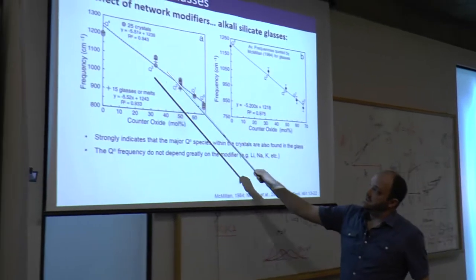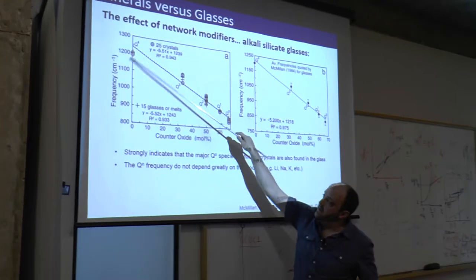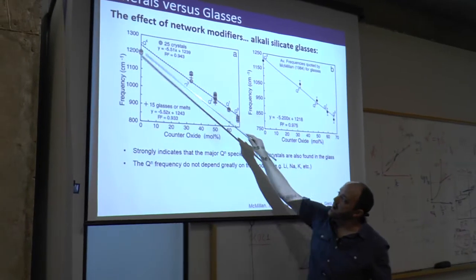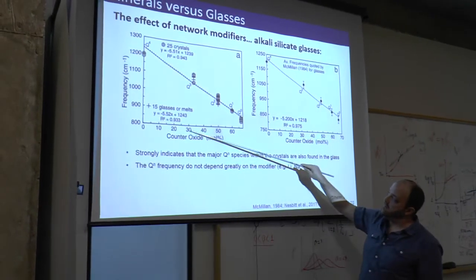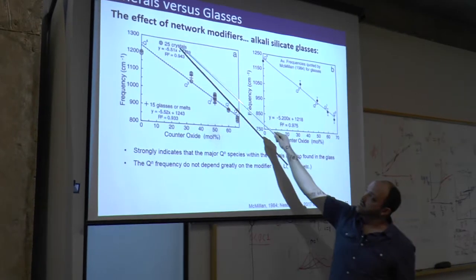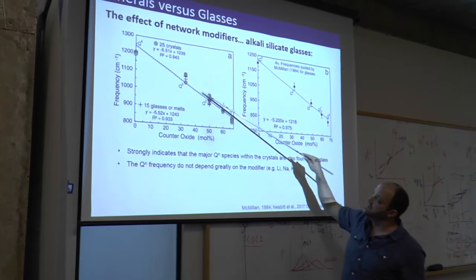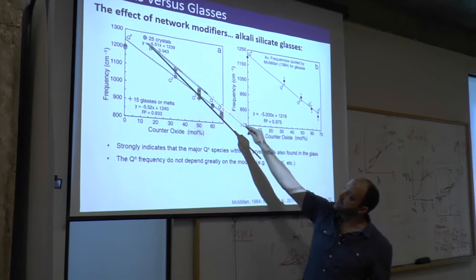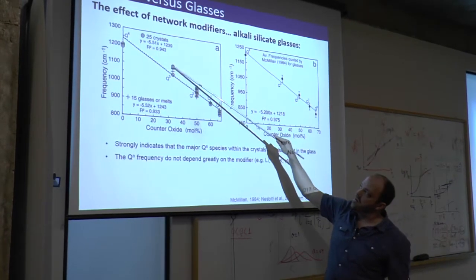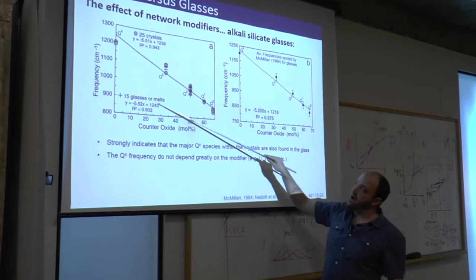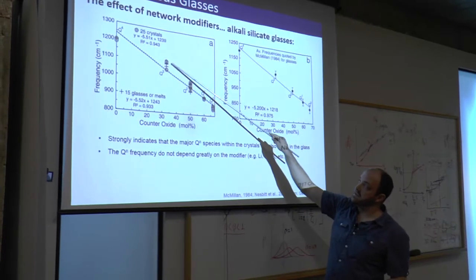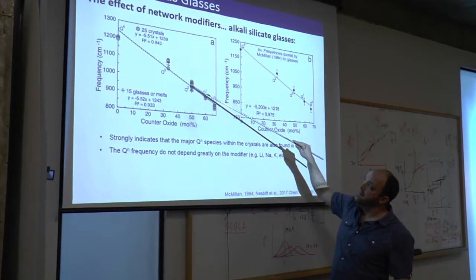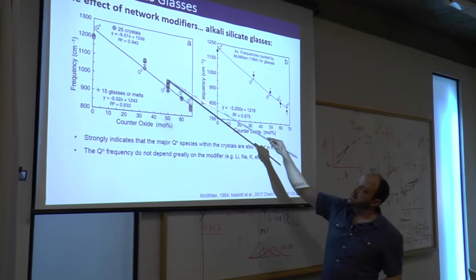And they plotted the position of these high frequency bands. So frequency is now increasing on the y-axis. This is the amount of modifier. And they showed for about 25 different crystal compositions in these circles, they actually sit almost on top of the glass compositions, the glass values for the same composition. You can see there's a little bit of spread here.